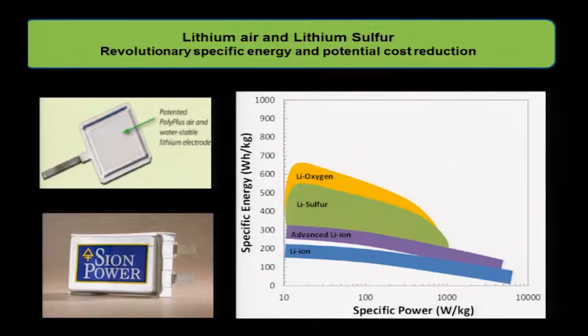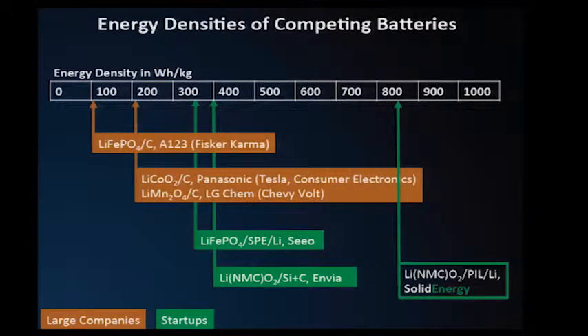Lithium. There's lithium ion, lithium air batteries. This slide was made about a year and a half ago. You see, two figures of merit are the energy in watt hours per kilogram, and also the power in watts per kilogram. And it's already out of date because advanced lithium is over 300 watt hours per kilogram. It's pushing 400 and above. There's even more afoot here to go well above 400 watt hours per kilogram.